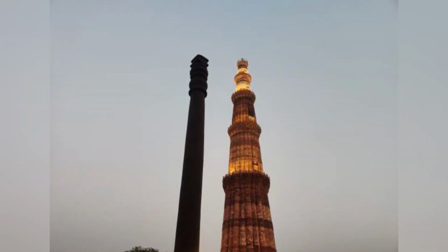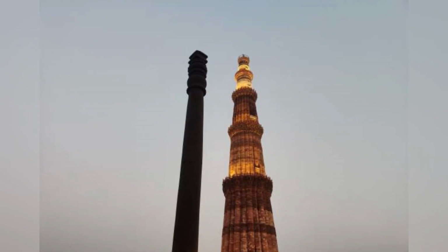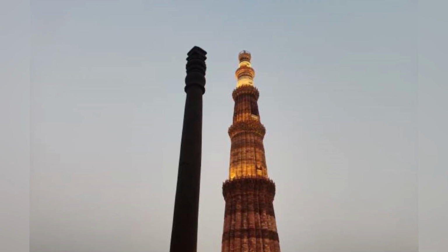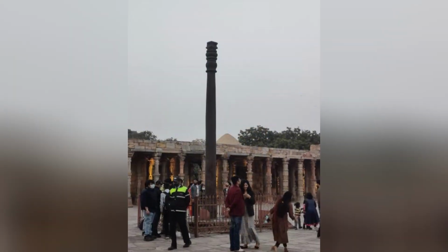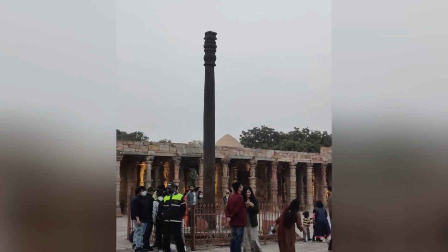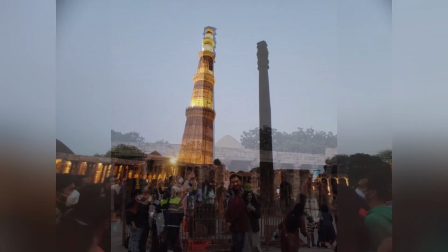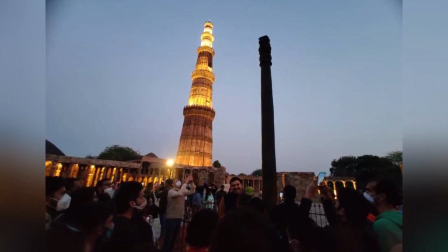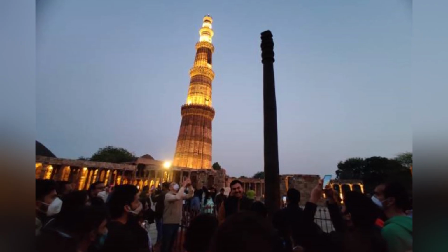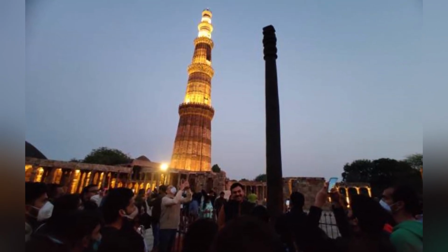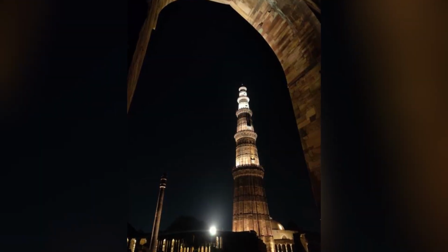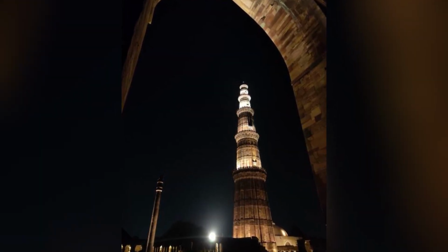The earliest chemical analyses of the pillar's iron were conducted in the mid-19th century, when British colonial officials commissioned the analysis of samples that had been removed from the pillar. These early analyses, which used the wet chemical methods that were standard at the time, revealed that the iron was of unusually high purity, with a low content of carbon, approximately 0.08%, and low contents of sulfur, silicon, and manganese, the impurities that are typically present in ancient iron. The early analyses also detected the presence of phosphorus at a concentration of approximately 0.25%, but the significance of this finding was not recognized until much later.